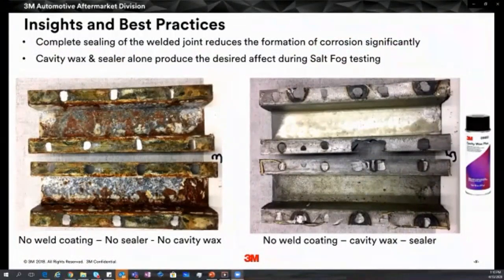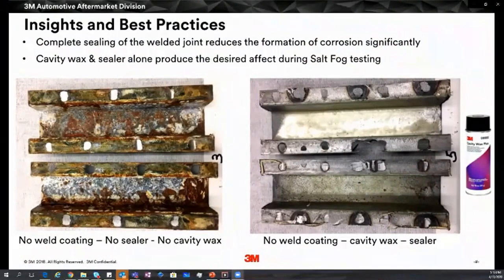And that left-hand image, the number three rail there, it has nothing: no weld through coating, no seam sealer, and no cavity wax. And on the right-hand side, that image has no weld through coating, but cavity wax, and then seam sealer around the outer perimeter of the joint. So we sealed that joint together from the outside. We didn't weld through the sealer. And then we use cavity wax on the inside.